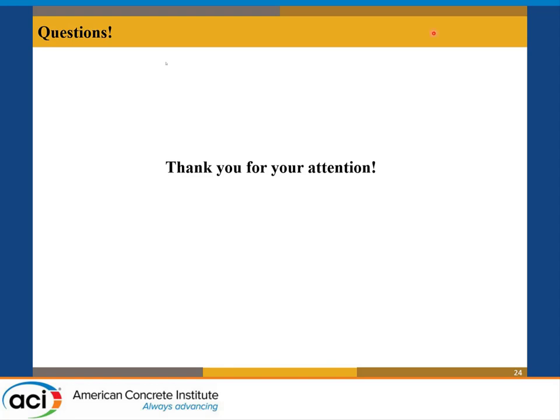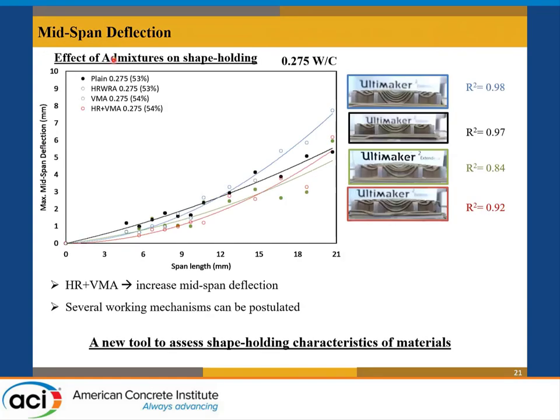The next question: as different admixtures influence extrudability, will they influence the buildability test? For example, the extruded material mass of each layer may not be the same — how can you respond to this? We actually measured this because we had all the volumetric CT data, the volumes, and the density of the material both fresh and hardened, so we could quantify the mass and normalize the data per mass. Once you normalize it, the difference between filaments in thickness and mass is not significantly different between one another, so it didn't affect the data.